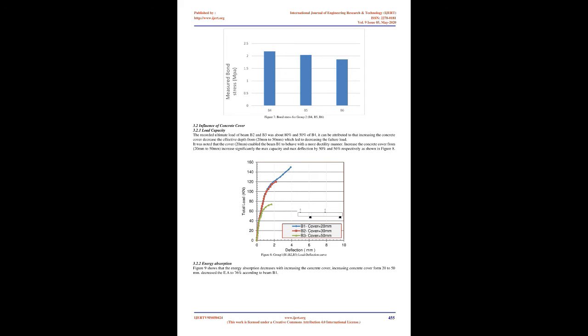The test specimens were tested under monotonic load. The load was applied with a uniformly increasing displacement until failure. All specimens were simply supported in a 4-point test as a beam with cantilever as shown in Figure 3. Each specimen was supported over 2 rigid supports with 1800 mm simple span with 600 mm cantilever span, and load was applied using a 300 kN capacity hydraulic actuator with max stroke 100 mm.